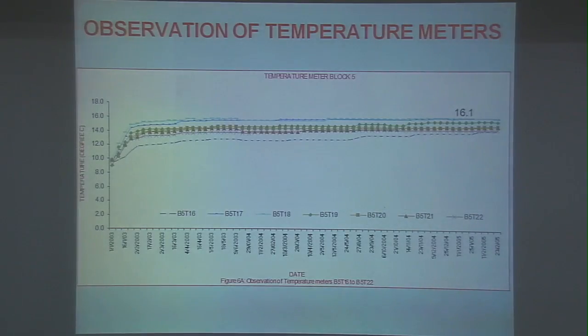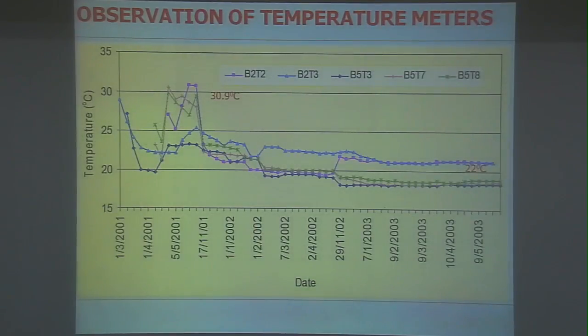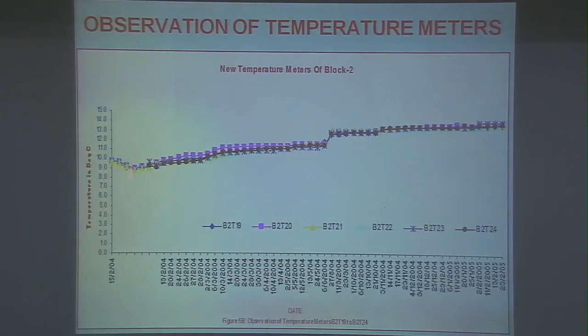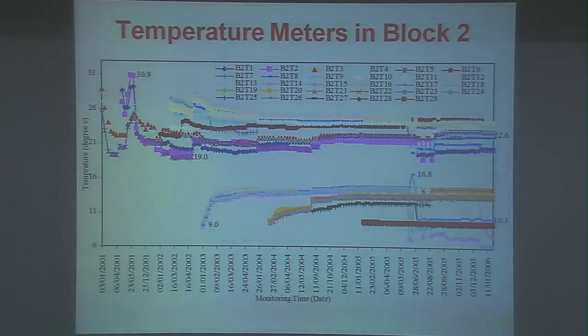So this temperature went up to 31 degrees, and it settled somewhere around 22 degrees in this case. From the next set of instruments, we started recording the placement temperature, and then the temperature rise, and the maximum was 16.1. This was because of the reduced cement content in the mass concrete. And you can see here the placement temperature was 10 degrees. Because of the low ambient temperature of 4 degrees centigrade, the temperature came down, and then it went up and settled around 13 degrees centigrade. So these are all the readings of the temperature meter.